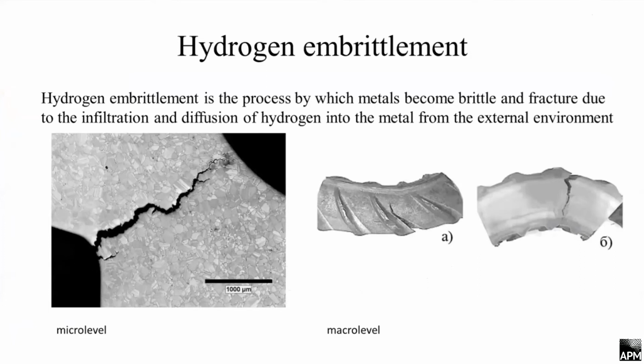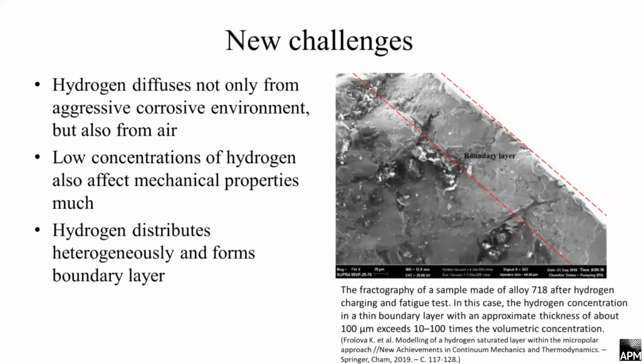We start from the actual problem happening everywhere, a well-known one: hydrogen embrittlement. It's the process when metals become brittle and have a lot of fractures because of the infiltration and diffusion of hydrogen into the metal from the external environment. This can happen at a micro level: a crack going through grains, and a huge crack after fatigue on macro-level samples of metal.